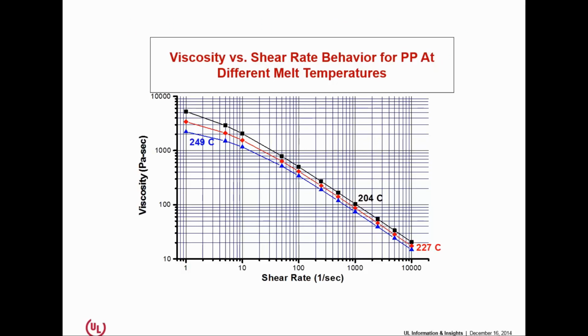So these are the 2 tools that we can employ in order to arrive at what we consider to be the ideal viscosity for the material, assuming you have a machine that can manipulate both of these variables at the same time. Now, what I almost always encounter when I walk into a molding plant is material running at a temperature higher than it should have to. And very often the reason is because people are out of speed, they can't increase the shear rate anymore, so all they can do is increase temperature.